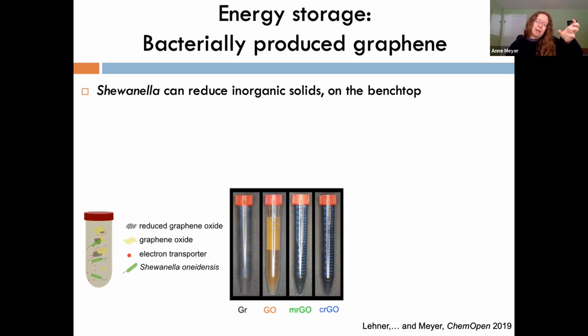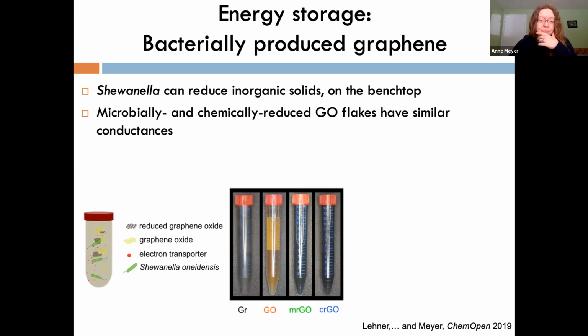So the first tube is a black tube of graphite. Next to it is a brown tube of graphene oxide. And then if you take our brown graphene oxide, mix it with the bacteria, and just leave it on the benchtop overnight, then we get, in the green label there, the microbially reduced graphene oxide. You see it turn black. So just by sitting on the benchtop overnight, our bacteria could reduce the graphene oxide to graphene materials.